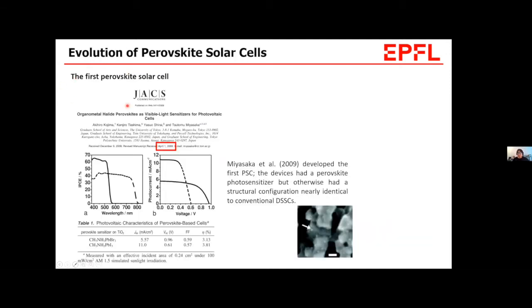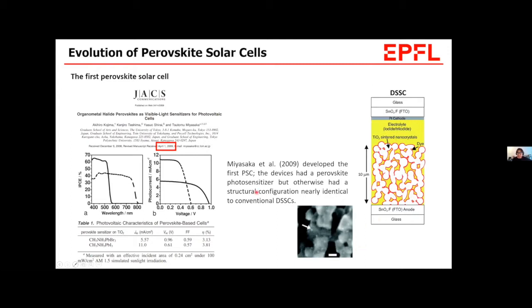So this is the first perovskite solar cell, but the structure is quite different from the state-of-the-art structure. Inspired by the high absorption coefficient of perovskite, it was employed as a photosensitizer instead of the dye in the conventional dye-sensitized solar cell structure. As you can see here, this initial structure had a thick mesoporous titanium dioxide layer, and the perovskite covered the surface of this mesoscopic titanium dioxide. But actually, unlike the fully covered titanium dioxide by the dye in this figure, the perovskite sparsely covered the titanium dioxide like this in this SEM image.